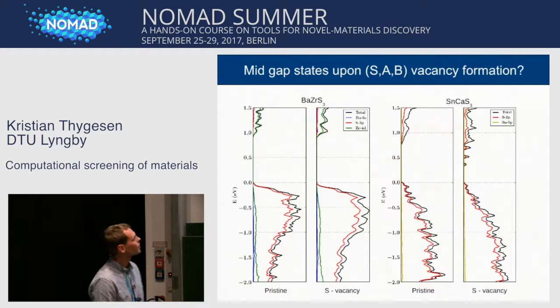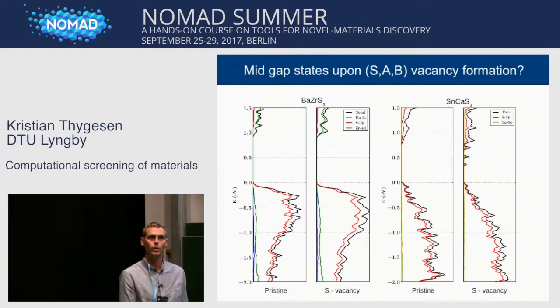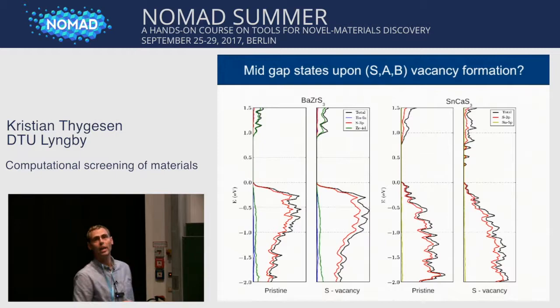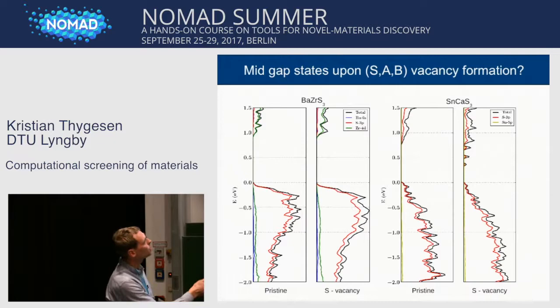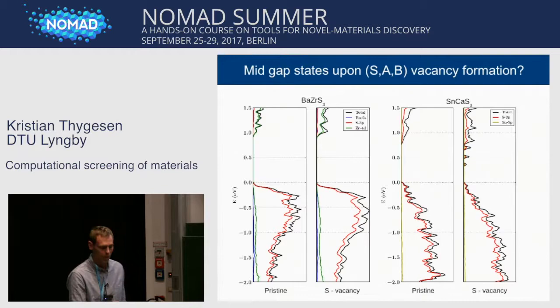Okay? So what we did is we took all of the materials that we have left at this point of our screening, and we simply created sulfur vacancies and vacancies of the A and the B metal atoms, and then we calculated the band structure and looked for states inside the band gap. And you can see here for barium zirconium, there is a case where for all the different defects, we still have the electronic structure of the pristine system present, so there are no localized states in the band gap, whereas for this case over here, you can see the formation of localized states in the gap. So this is really a killer for optoelectronic applications of this material, and we exclude all the materials that form deep mid-gap states at this level of the screen.